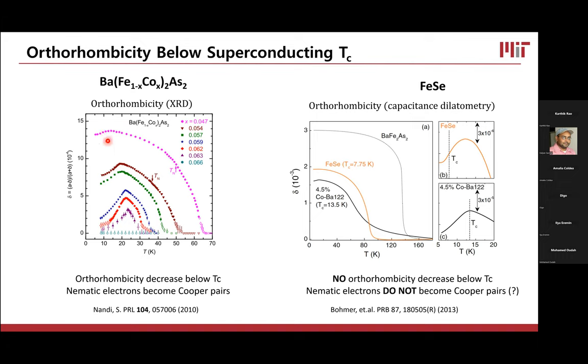And something really cool happens. As you go in doping towards stronger superconducting orders, the orthorhombicity becomes more and more suppressed by the onset of superconductivity. For instance, if we look at this blue one, we hit a nematic transition, the orthorhombicity increases, we hit the superconducting transition, and the orthorhombicity decreases. And for some dopings, if you get right towards the critical point, you can suppress it entirely. So this plays into this story that these nematic electrons are converting into Cooper pairs, which is another part of the story that fits really nicely with this idea that there's spin nematicity, and critical behavior of those spin fluctuations gives you the superconductivity at high temperature. So this piece fits really nicely together.